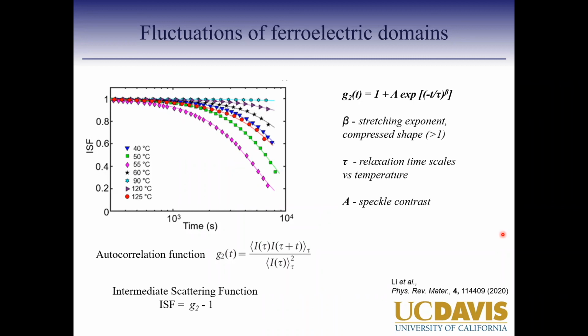So I don't really want to comment on exactly how it varies, and I don't remember how much it was for the other systems. But from what I remember, for some of these orbital ordering and charge ordering systems, it has been higher than 1, somewhere around 1.5. And that indicates glassy dynamics in these systems. Which is fascinating in a way, right? These are crystalline systems, but the ordering, these superlattice orderings, are acting more like a glassy material.